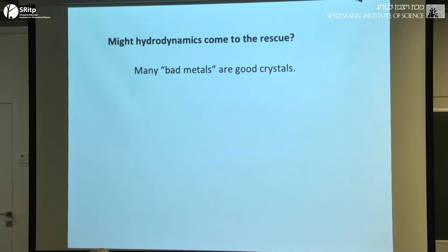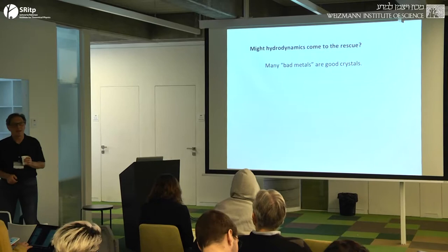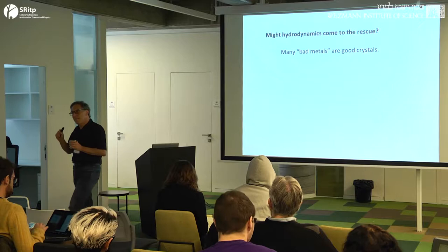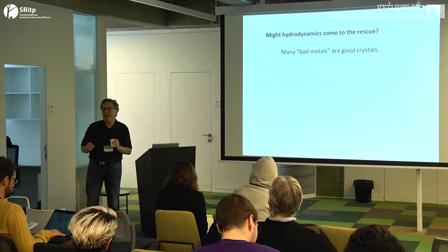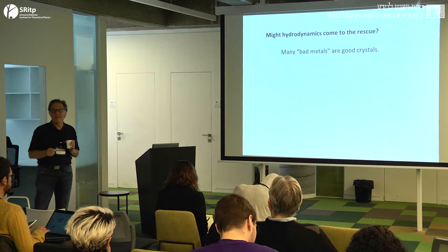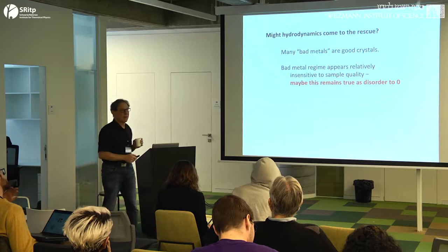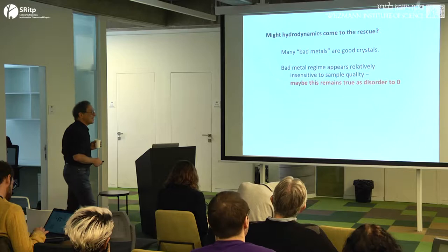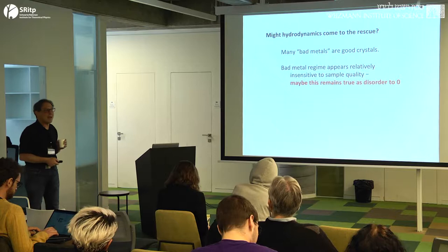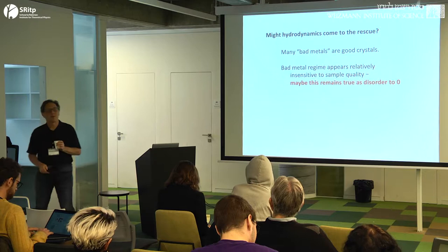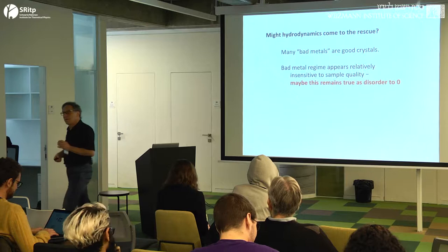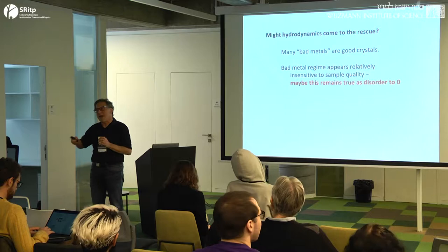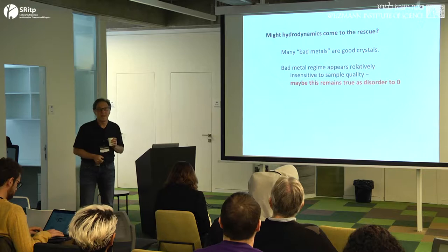Well, first place, these bad metals are seen in good crystals. That is to say, people have spent an awful lot of time and effort making the best possible crystals they can. These are very good crystals by most metrics of solid state physics. They're very pure. They have very sharp coherence peaks. And moreover, this bad metal behavior seems to be fairly insensitive to sample quality. So you take the best crystal that anybody's made, and you take some crystal that somebody made in their garage with a Mr. Superconductivity kit, and their resistivity in this T-linear regime are pretty similar to each other. So maybe that gives you an excuse to say that maybe we can extrapolate to the zero disorder limit, that disorder is having a negligible effect there. And so one of the enemies of hydrodynamics, maybe we can discount.